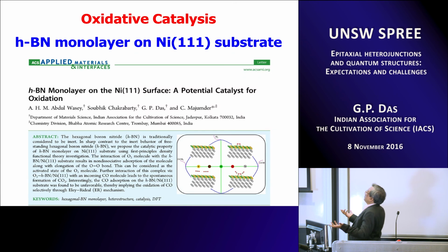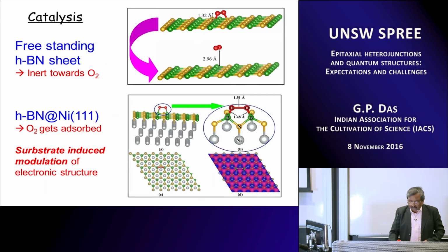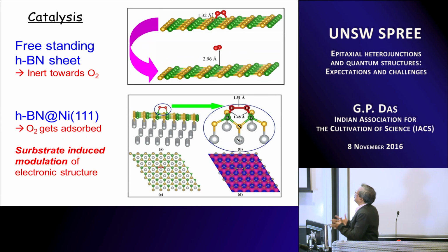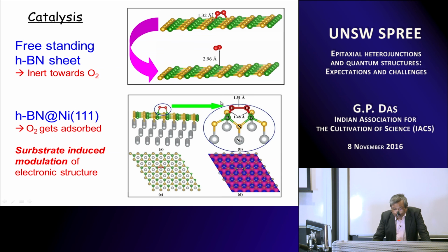However, something very interesting takes place when the same hexagonal boron nitride you put on a nickel 111 substrate. Let me show you pictorially without going into any detailed numbers. See, a freestanding hexagonal boron nitride sheet is this one. When you are trying to bring an oxygen molecule O2 to that and do a full-fledged ab initio molecular dynamics, we find that, unfortunately I do not have the video, otherwise I could have shown you, that the oxygen does not like to stay, it goes away from the surface. This is for a freestanding hexagonal boron nitride sheet, so it is inert.